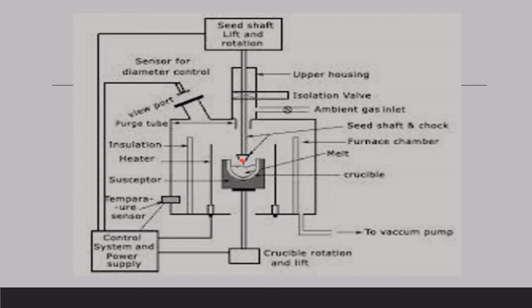If you pull up very fast, you may not get a single crystal, and if you pull up very slowly, you may even get the seed crystal melted. So this pull up rate is very important in this case.